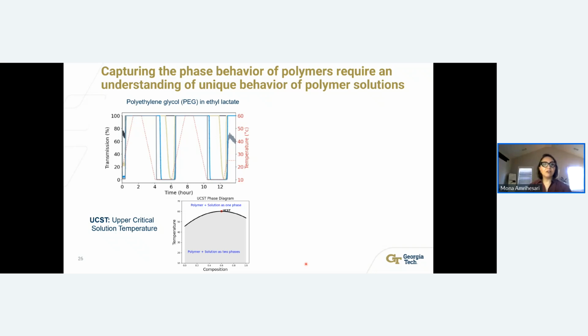This is an example of polyethylene glycol in ethyl lactate over different concentrations. Again, the black line is 5 milligram per milliliter and goes to 50 milligram per milliliter for the gray color. This polymer specifically has upper critical solution temperature, meaning that at higher temperature, polymers start dissolving fully in the solution and become one phase. And as we change the temperature to bring it down to a lower temperature, here at 10 degrees C, the polymers start precipitating and phase separation is happening.